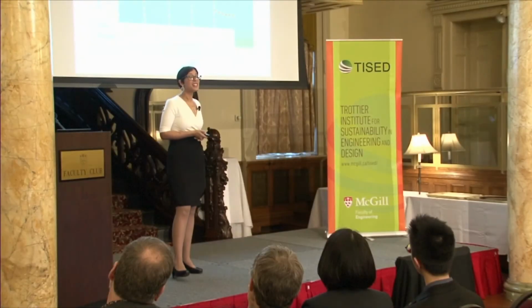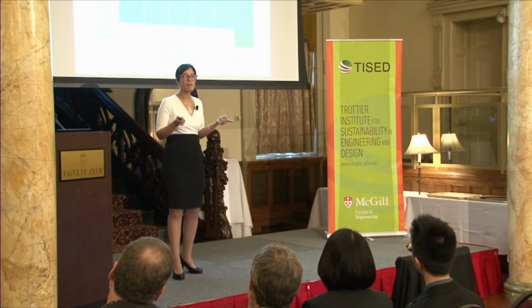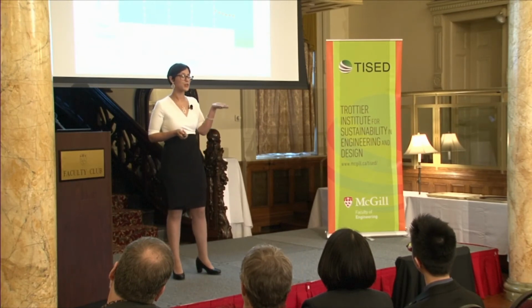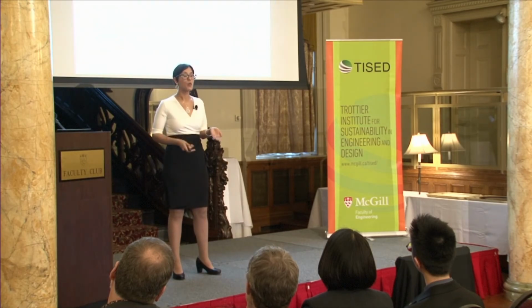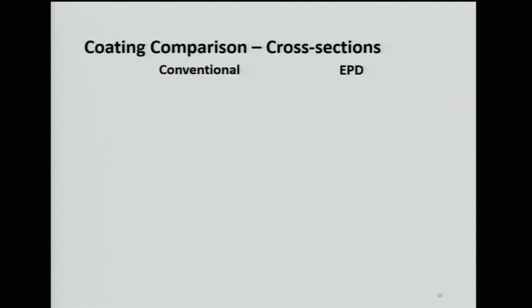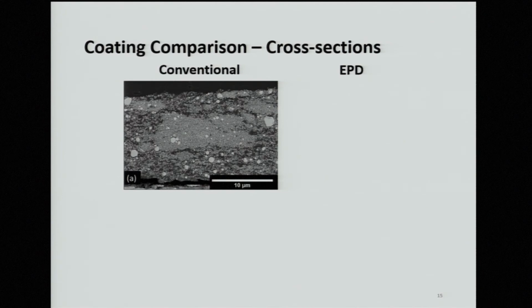That's great. But now we need to know why. And the difference between these two was the way that we made the electrodes. So we took these electrodes, or the coatings, we cut them in half, and we imaged the cross-section. So up here, I have a scanning electron microscope image of the cross-section of the conventional coating along the thickness. And the first thing you might notice is this chunk in the middle. What is it? You see, we have 3 different types of materials, right? We have the lithium titanate, we have a carbon, and we have a binder. So how can we know what this is?